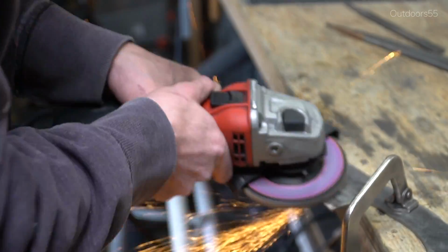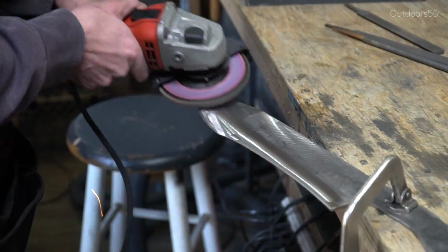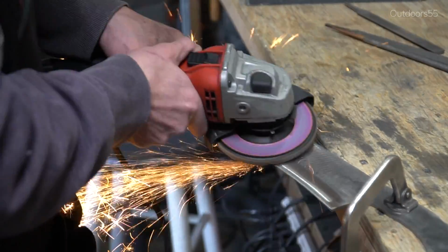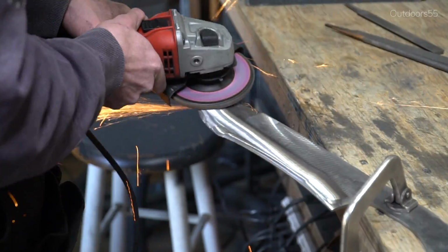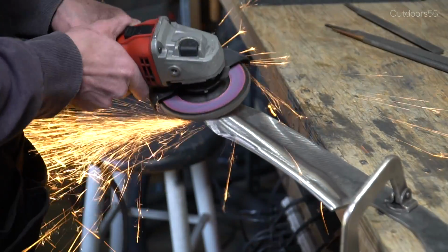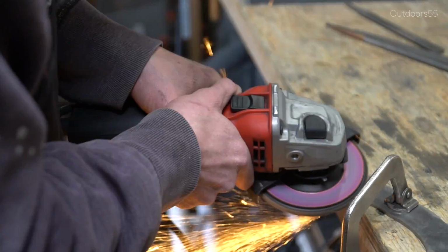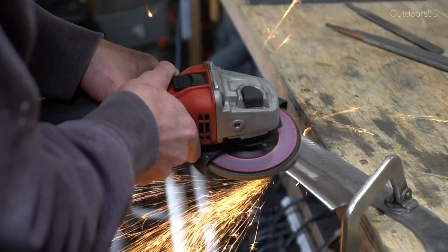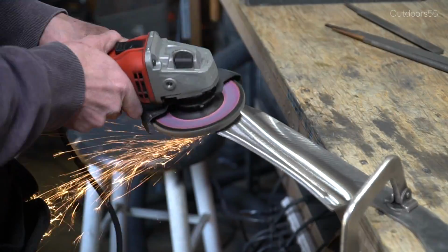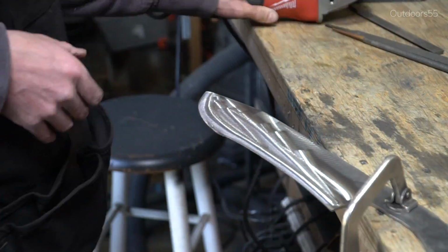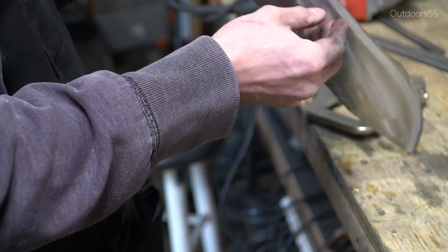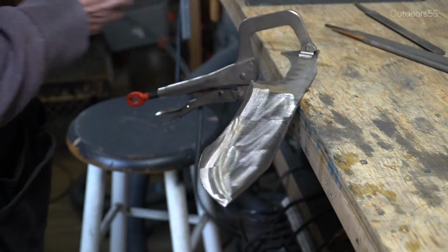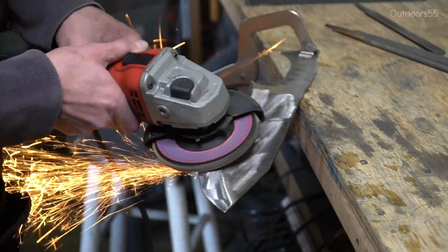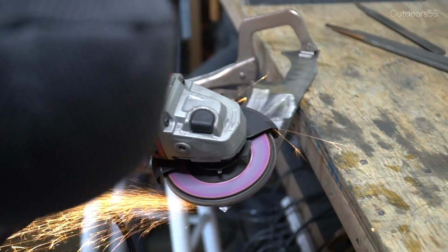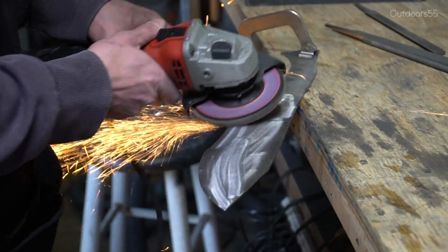The reason that you want to do this is because during heat treatment, thicker sections of the knife will actually cool down slower than thinner sections. And if you have a bunch of thin and thicker sections unequally distributed along the entire length of the blade, you'll have unequal cooling and thus create a warp. Now we're using an angle grinder here. We're not using super precise pieces of equipment. So just do the best that you possibly can with it, and it should be okay.